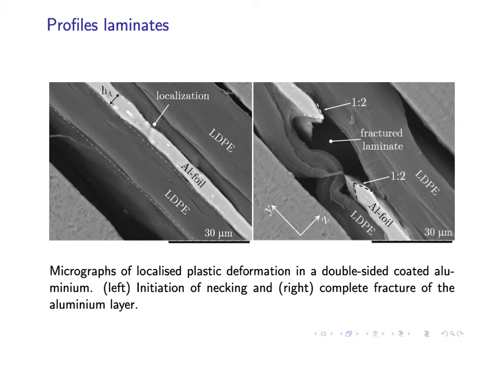On this slide you see two pictures from a scanning electron microscope, and these are cuts across the crack plane, and you see the aluminium foil, and in this case there are two polymers on each side of the aluminium foil, the LDPE. And what you can see is an indication of localization of strains at one point, and this is a cut taken ahead of the crack tip, not too far away from the crack tip, but still ahead of it.